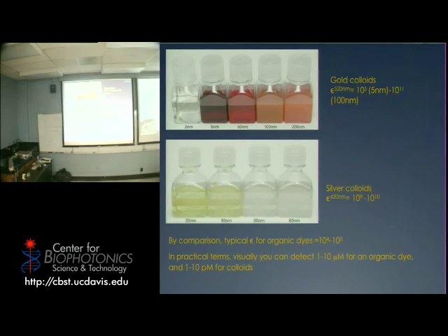So, are you guys familiar with the concept of extinction molar coefficient? The extinction molar coefficient is essentially a chromophore dependent value that gives you an indication of how much light you can absorb. And the larger it is, the more intense the color is at a certain wavelength. So the bigger it is basically means that it's easier for you to distinguish it at low concentration. So even the best chromophores that you can find, at best, have an extinction molar coefficient of the order of 10 to the 4, 10 to the 5. So say 100,000 maximum, maybe 150,000 maximum.